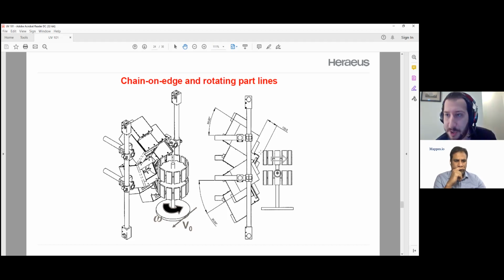For larger 3D parts, you might need multiple lamps positioned at multiple angles. So this would be an example of cell phone cases that are cured with UV energy. You have a rotating rack, which has parts all around it, and UV lamps, which are arranged at high angles, medium angles, and low angles, so that no matter what part of the case gets exposed to the UV, it's all going to be dried and uniformly cured.